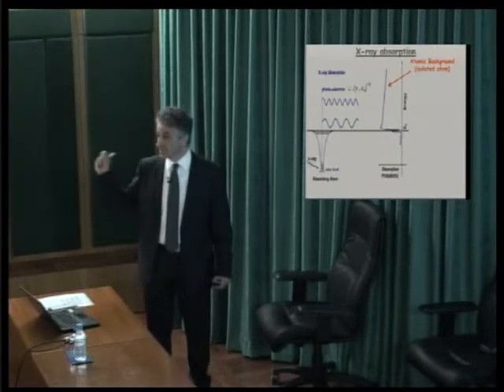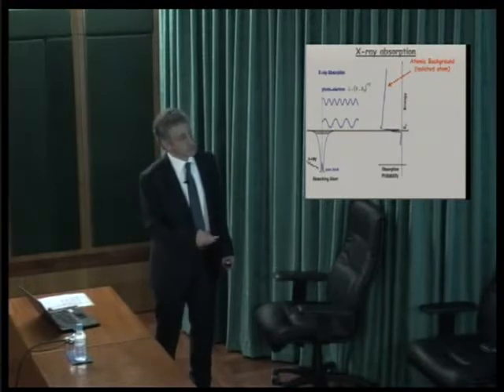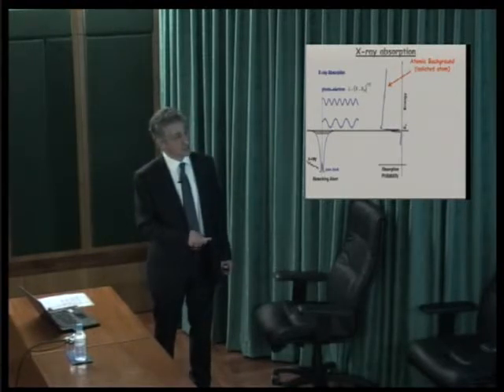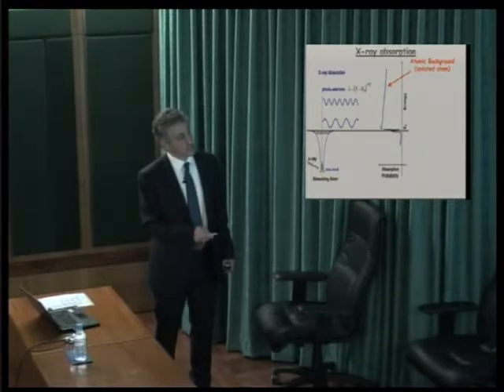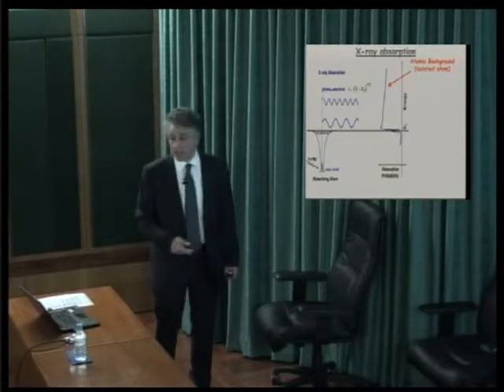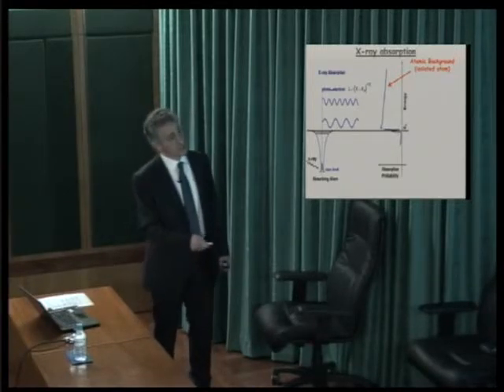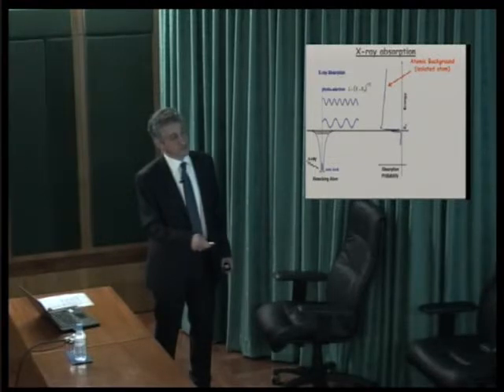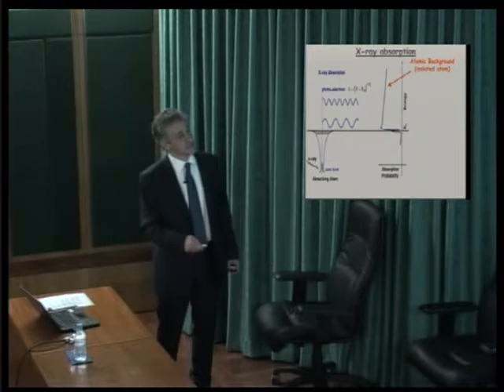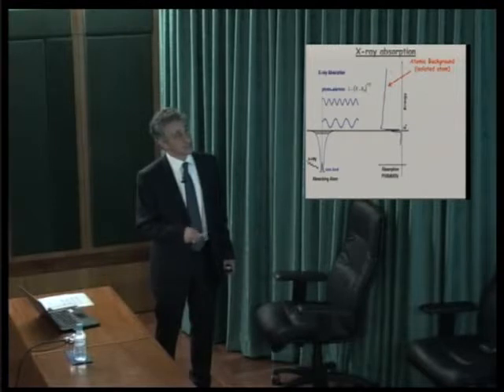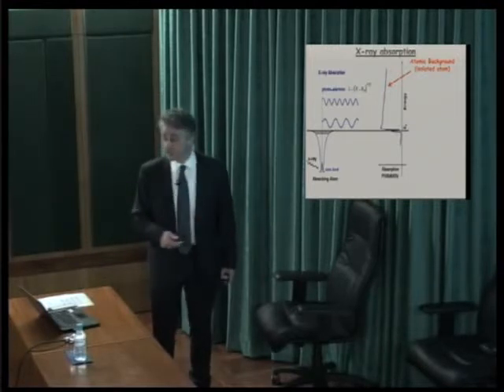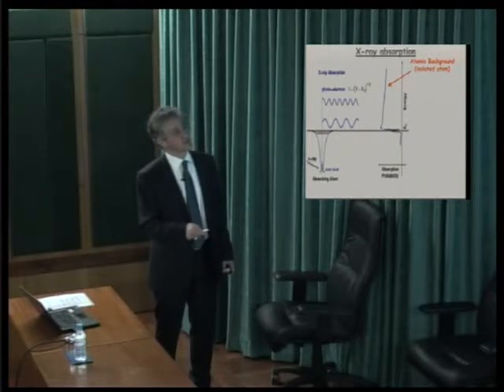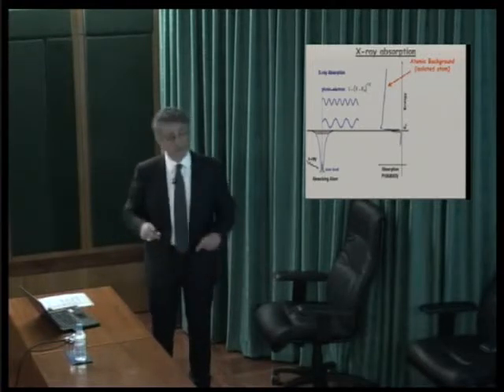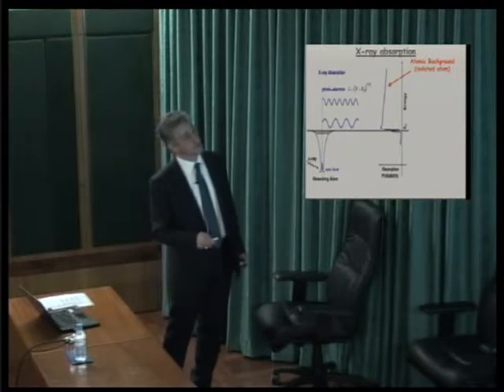If you take the atom isolated, and you have the Coulomb potential of the atom, and you extract an electron from a core level, you tune across the ionization limit. If you have empty valence orbitals, and if the transition is allowed by atomic selection rules, you might get bound-bound transitions just before the ionization threshold. So these are below the ionization. And then as you cross into the ionization, you have an edge jump and then a flat background. That means in this region, you are producing a photoelectron. And the de Broglie wavelength of the photoelectron is given by the excess energy above the ionization limit, and it scales as the inverse root square.